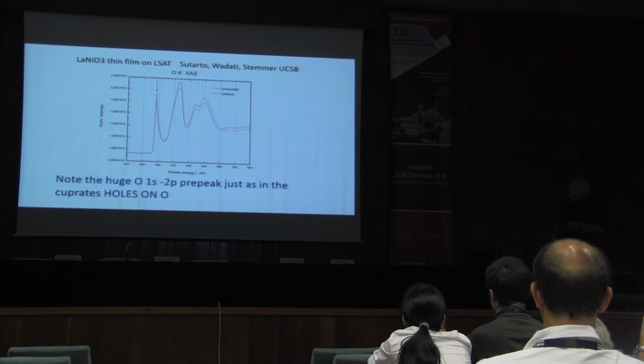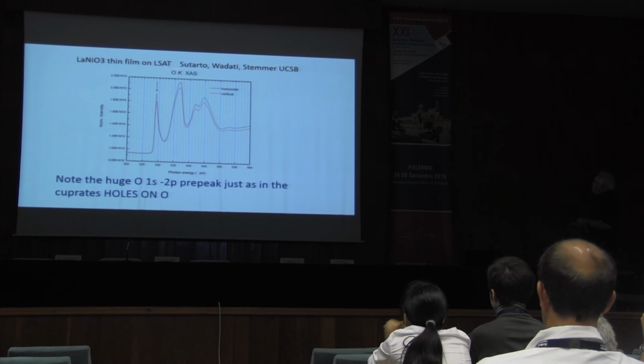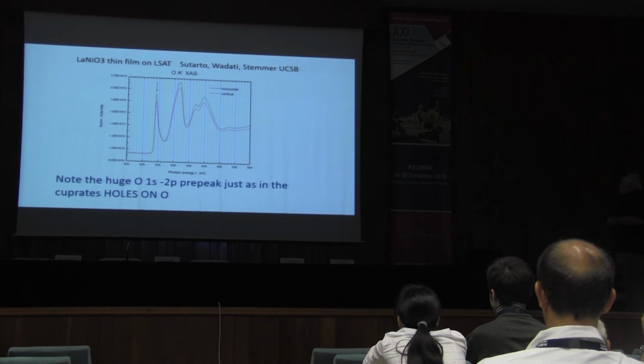Going on, so this is nickelate, lanthanum nickel O3. And there also, the lanthanum is 3+. The nickel should also be 3+ if you have 3 oxygens, which are all 2-. This is for a thin film, actually, grown epitaxially on top of LSAT substrate.